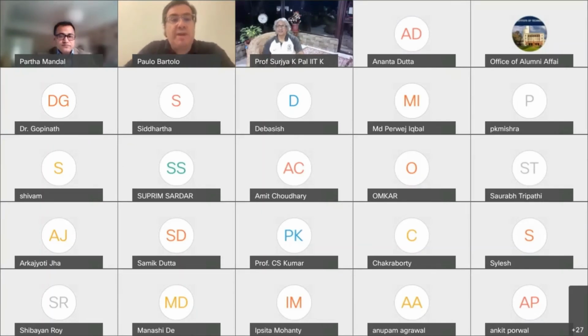So what we knew from the scaffold is that if you control the microporosity, you increase cell adhesion and differentiation. We decided to do the same with our bone fixation plate. So once you printed the structure using electron beam or selective laser melting, the surface presents some roughness. So we decided not to post-process the plates. And when we compare our plates with polished commercial plates, we observe a significant difference. So cells were able to grow in our plates and not able to grow in the commercial plates. And we assume that our plates, once implanted, will create a better tissue interface with the surrounding tissues.